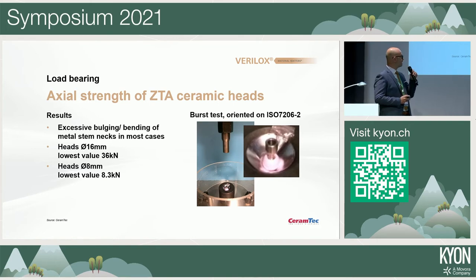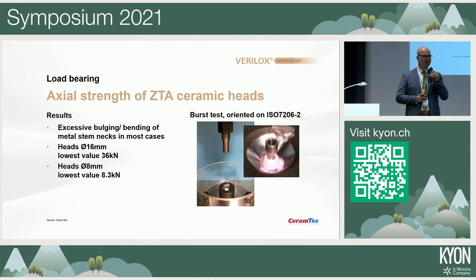What we saw there, that in most of the cases, we got an excessive deformation of the metal parts. And in some cases, we were able to fracture the ceramic heads. And the values that I show you here is for a 16 millimeter head, we got a lowest fracture value of 36 kilonewtons. Please think on that. 36 kilonewtons force, that's comparable to 3.6 tons, metric tons. So that is what you can apply in axial direction onto these heads before you fracture them. And then it makes sense that we also have seen a huge deformation of the metal parts.